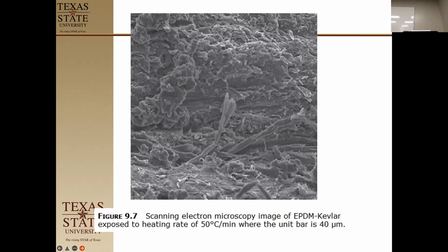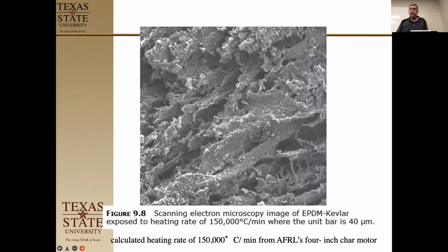Well, then they went off and ran an experiment with an actual motor, and they calculated the rate of heating of this motor, it's a 4-inch char motor. So basically, they power it with liquid diesel and shoot it at your sample, and it's 4 inches in diameter when they do it. And they calculated the heat flux to be 150,000 degrees per minute. Okay, so rocket motors are a lot higher, right? And notice this looks completely different. We have the nanocomposite, the nanomaterial is charring on the edges here. We have a lot more porosity. We have a different structure here. And notice we have flow. So you have a little bit of flow that you can see it's all going kind of in one direction. So we have that melt phase happening as well.